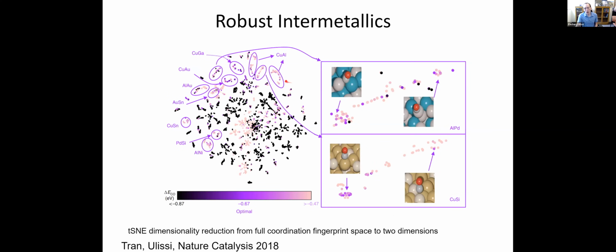The ones that we focused on initially were binary combinations where it seemed like no matter what we added, it would help the process. So on this map, this is a T-SNE map. We want things in this deep purple region. And so things like copper aluminum, no matter how I add aluminum to this copper, it seems like it helps to weaken the CO binding energy a little bit. And that's supposed to have a good impact on CO2 reduction.